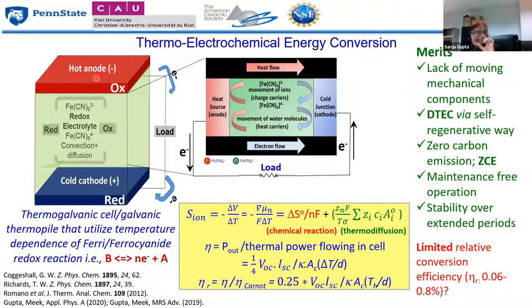Because of the temperature difference, with temperatures that we typically use from 40 or 50 degrees to 100 degrees Celsius, this allows us to have a reduction and oxidation: oxidation at the hot anode and reduction at the cold cathode. And as a result of the separation of the charge, the electrons start to flow. And then of course you can extract that energy and convert it into power, thermopower. So instead of an electronic Seebeck effect, you have an ionic Seebeck effect.